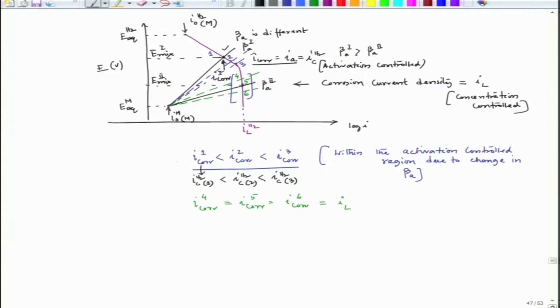So, the same situation, because we have to follow the mixed potential theory, where at some mixed potential the rate of cathodic reaction is equal to the rate of anodic reaction. But in this situation I could see that E mix is changing. So, if I try to see the corresponding E mix values, this is E mix 2, this is E mix 3. And if I point this one as E mix 1, then E mix 1 is greater than E mix 2 greater than E mix 3.